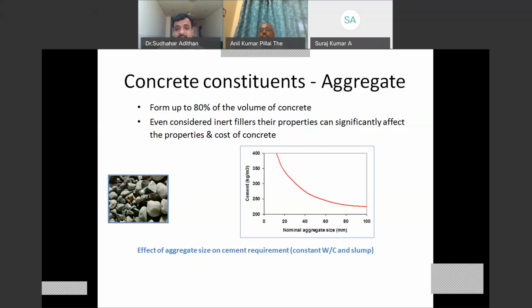The size of aggregates does matter, as we were just discussing. If the size of aggregates goes smaller, then the requirement of the binder becomes larger. As you would appreciate, for the same mass, if you have two different sizes, then the finer system would have more surface area, which means it needs more binder to coat itself. So as a result, you will require more cementitious content in your concrete system. This graph is a simple depiction of it. Don't take the values, but look at the pattern of the graph. If your nominal aggregate size is increasing, the requirement of cement will come down.